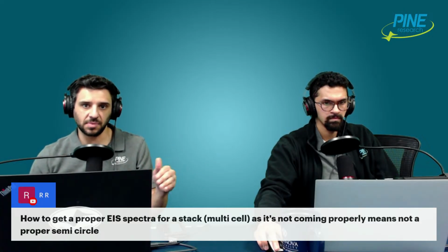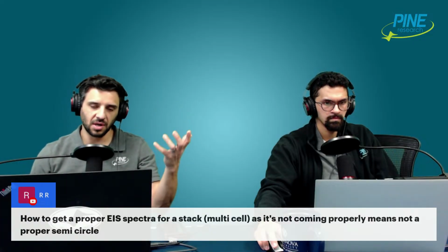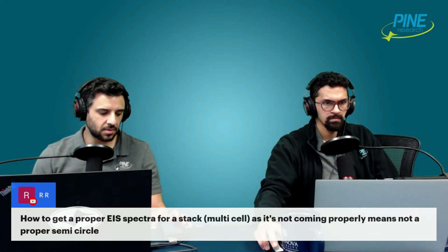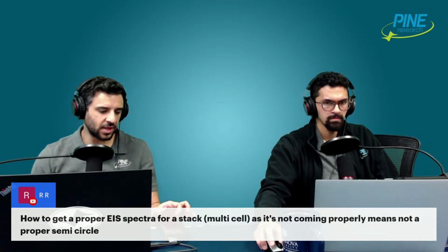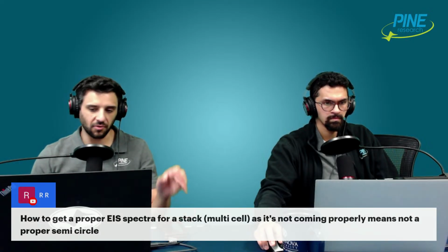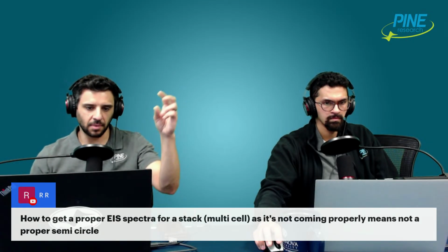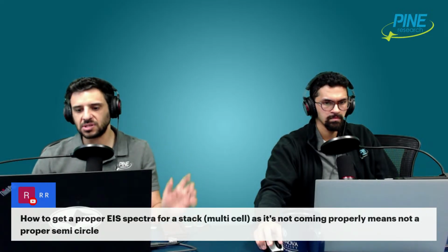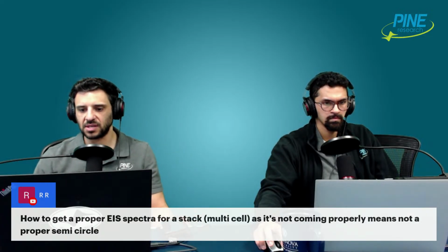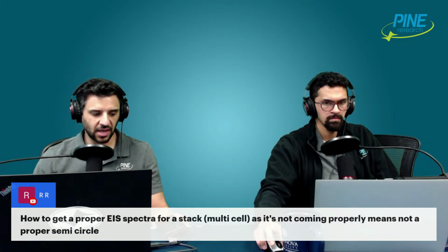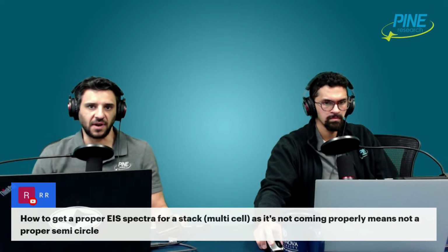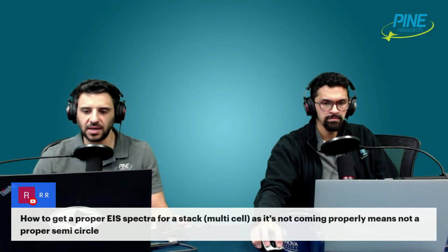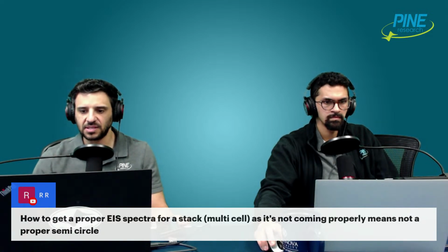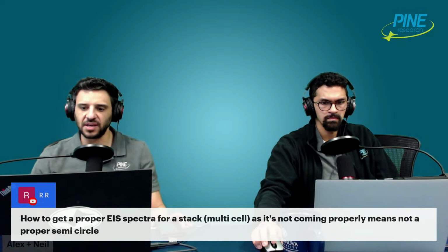That's where you can get dangerous, because then you could overcharge or over discharge, for instance, when you proceed as normal without taking into account that one cell is already too high or too low compared to the rest of them. So those are just some of the thoughts I have about that. Of course, as a general rule, I can't speak perfectly well to it if I don't see the data, but hopefully that's some general advice for taking impedance on those kinds of systems.